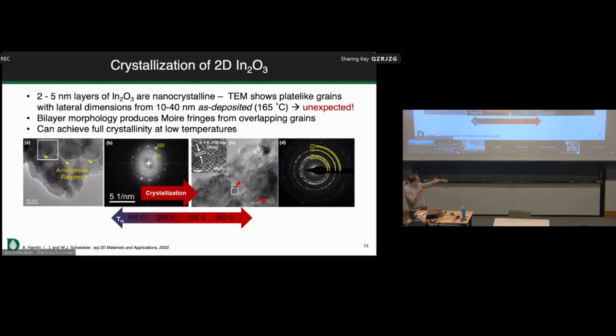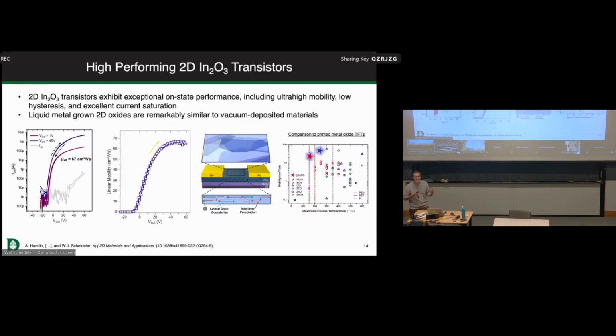As you crystallize it, you see another interesting feature. If there are any electron microscopists in the room, you might recognize that there are these tiger stripe looking things called moire fringes. The moire fringes indicate that we actually have independent crystallites stacked on top of one another. So this is like a physics problem from high school, if anyone's ever seen it. The period between those two stacked crystallites of their atomic fringes gives us this emergent pattern when we stack the two.